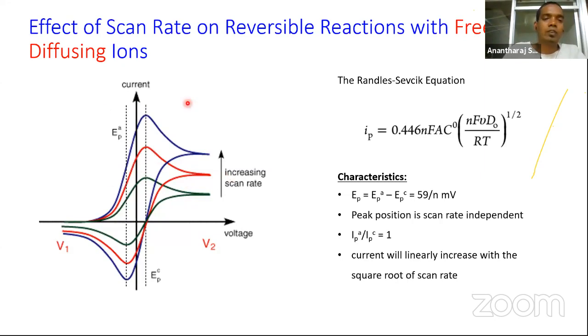So in CV, when we have diffusion control and we increase scan rate, this is what happens. The current density increases, but the peak-to-peak separation remains the same. In the other case, if you take the peak current ratio, the ratio between anodic peak current and cathodic peak current, it will be exactly equal to 1. And the current will increase with the square root of the scan rate.